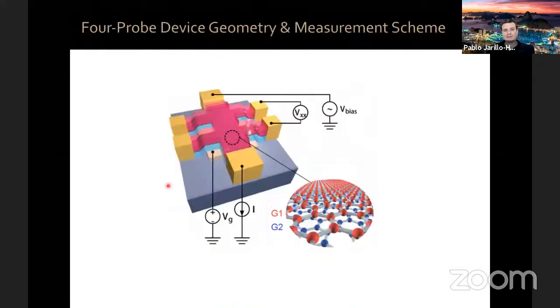we prepared new samples in a four probe device geometry so that we can run a current and measure the voltage drop intrinsic within the device and see how well magic angle graphene wants to actually conduct. When we prepare these devices, the first thing that we do is measure them again in a two-terminal geometry because it's easier to characterize them first in that geometry.